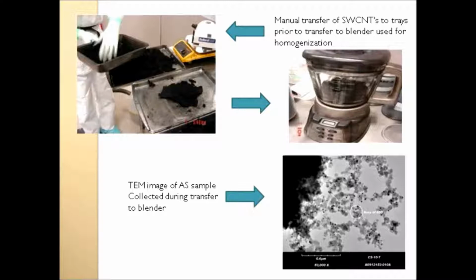Here again, he's doing another handling task involved with this process. He's transferring from tray to tray to undergo a baking operation, and you can see that there are no controls here. In fact, they're using a regular household blender to homogenize this material to break up these clumps. They don't want it clumpy. We collected a sample right near the transfer operation. I'm not sure if you can really see it. It might be in the background. During this operation, you can see that there's a lot of material that comes off. This stuff is light and fluffy. It does tend to become airborne. And here's what it looks like under TEM.